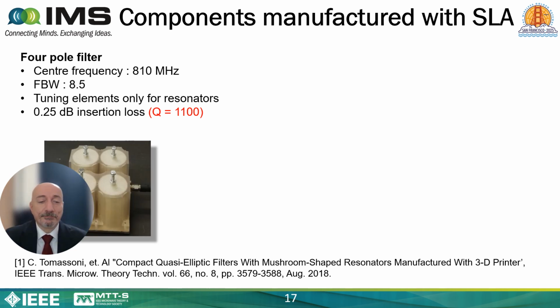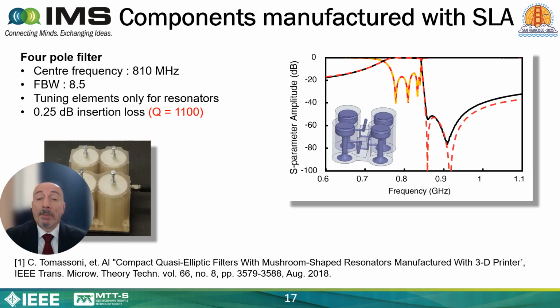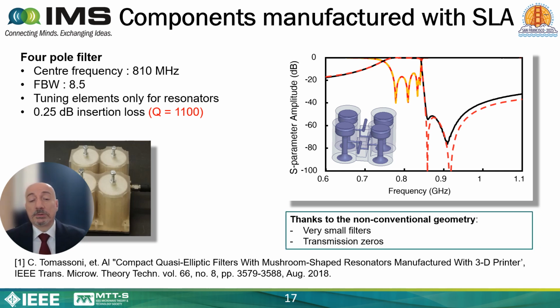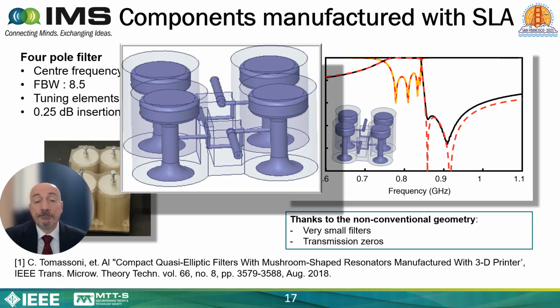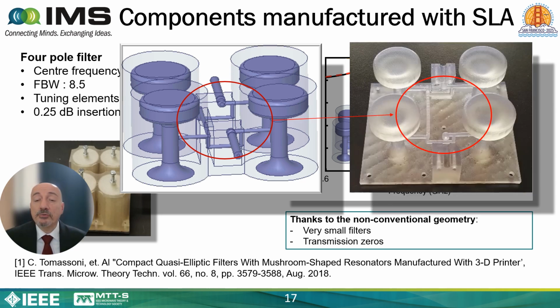And this is the manufactured filter. As you can see, this is the assembled filter, and the metallization is visible, and you can see that it is only inside because the external part has not been metallized. But in any case, this is the comparison between the manufactured filter response and the equivalent circuit response. What I want to point out is that thanks to the non-conventional geometry, this filter is quite small, and we also have transmission zeros that can be easily controlled. And this is obtained thanks to the versatility of this technology. Indeed, this is the complex structure we have to manufacture, and this part, as you can see here, has been manufactured in only one shot.